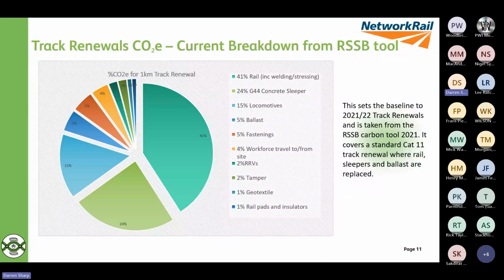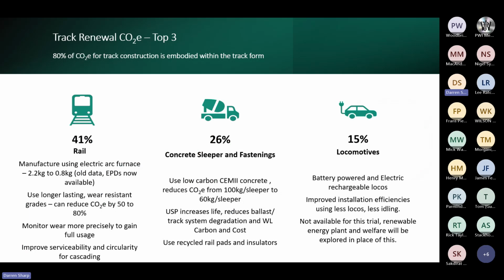So looking into track renewals and the CO2 in track renewals, some of you may be aware of the RSSB carbon tool. So we use this as a sort of 2021-22 track renewals baseline, and that's where we were able to look at what percentage each material type adds to this. So 41% is rail, and that's including the welding and the stressing. So that's all installation, rail, welding, stressing. Then concrete sleepers, then locomotives, and then ballast, and then we start to run down to fastenings, workforce, and tamper, and so on. So the top two materials really are rail and concrete.